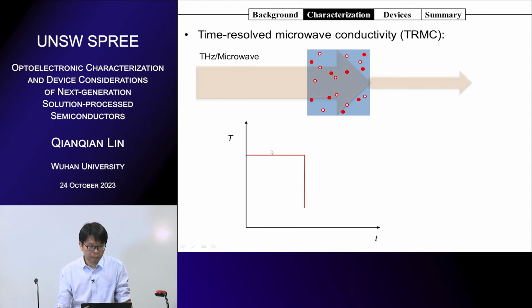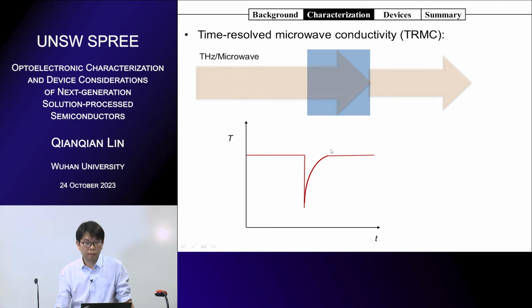So the transmittance reduced immediately because the laser pulse is very short, normally around 1 nanosecond or less than a few nanoseconds. So we just get a drop of the transmittance. But the carriers cannot live long. They will recombine. So electrons meet holes, they get emitted, so we get radiative recombination. And the carriers can also be trapped, and it can be lost as heat. So the carriers will recombine radiatively or non-radiatively. Finally, the carriers will disappear, and we can get a recovery of the transmittance.